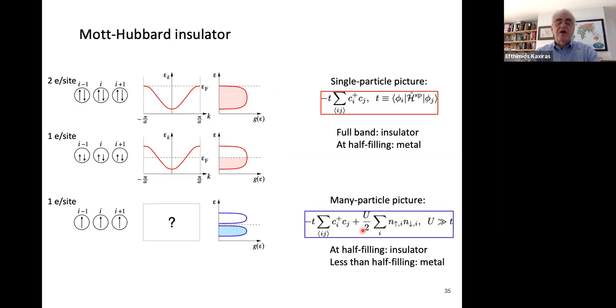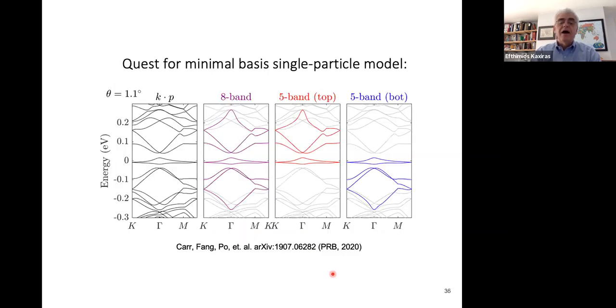So in order to now capture the physics using a Mott Hubbard insulator picture, you need to have as few single particle states as possible to make a realistic scenario and also check it numerically. And this is not easy if you have many states. Hence the quest for a minimal basis single particle model. So we've been working closely with Ashwin's group to produce such a minimal basis model. So here is the full set of bands that we need to describe everything from our ab initio theory. Here's a subset of 8 bands around the Fermi level, capturing at least the essential behavior.